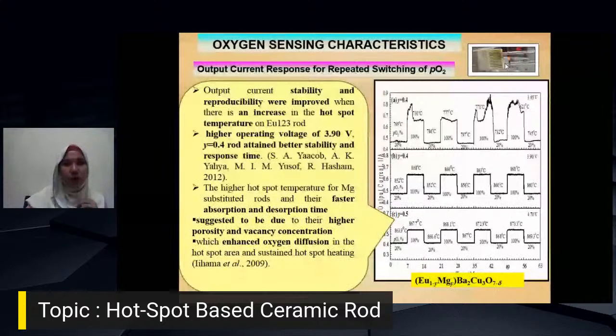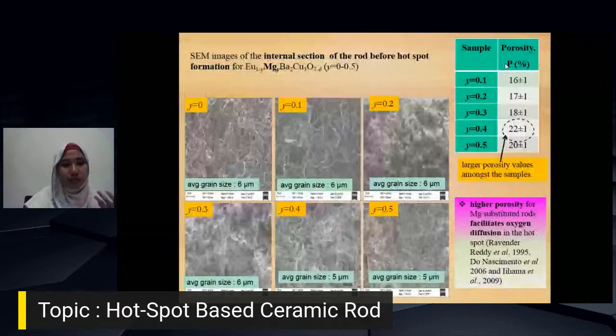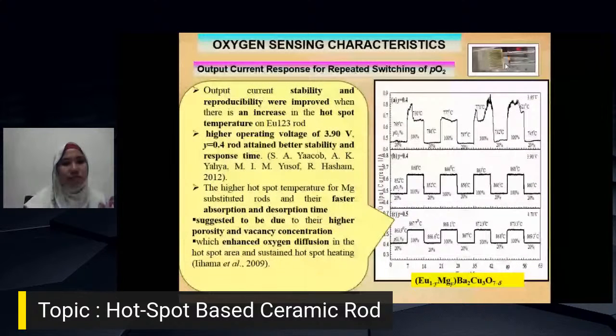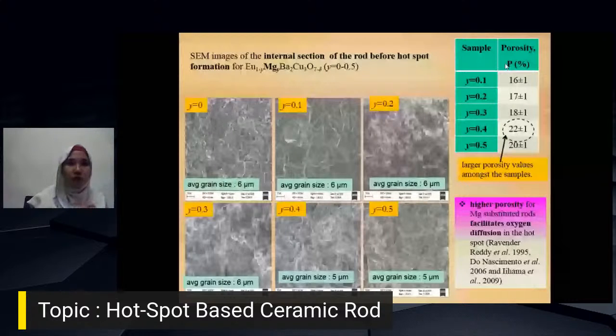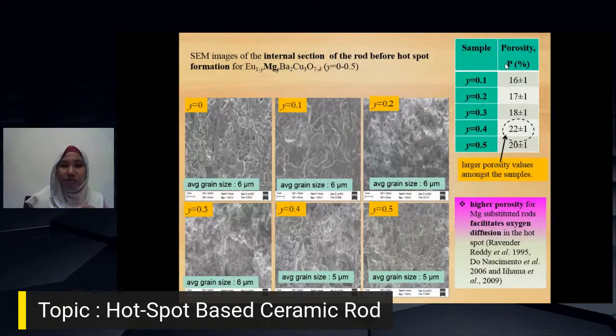Next, previously I explained that it's related to concentration. This is a scanning electron microscope image of the internal section of the rod before hotspot formation. The SEM image can show the average grain size of the compound of the ceramic rod, and show that when you increase the magnesium in the rare earth, the porosity also increases. The higher porosity for the magnesium-substituted rod facilitates oxygen diffusion in the hotspot.